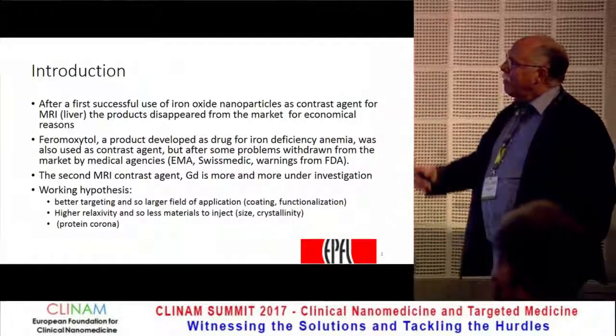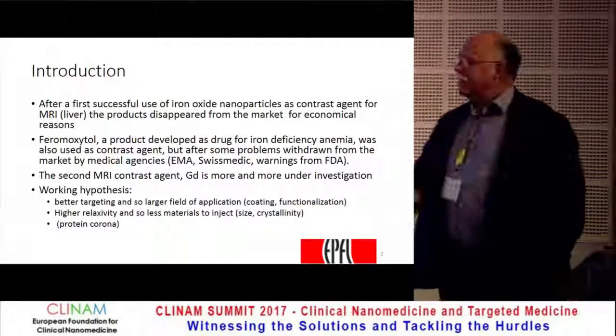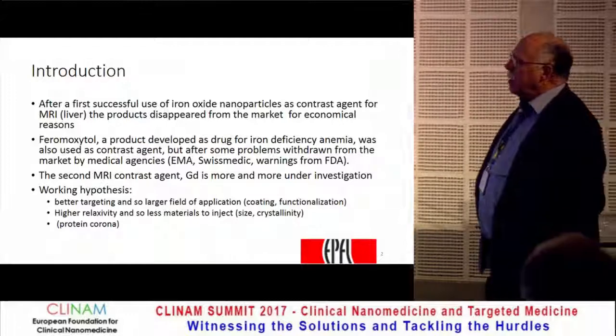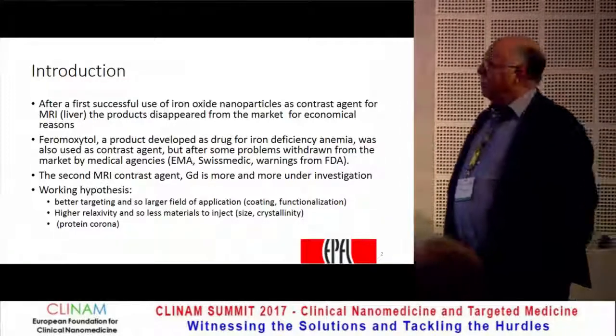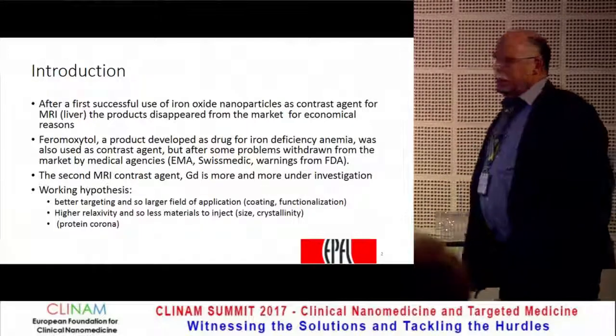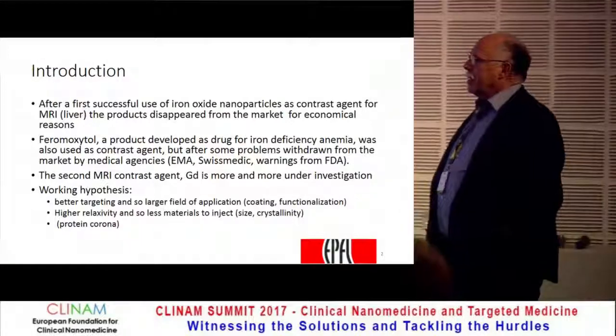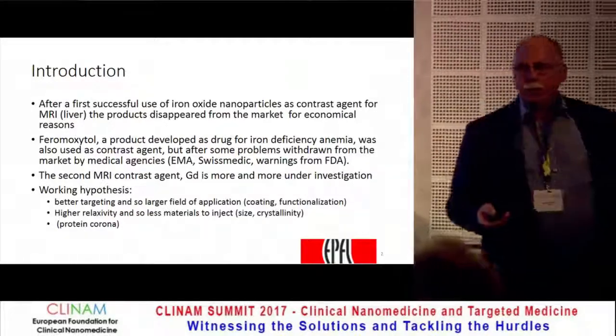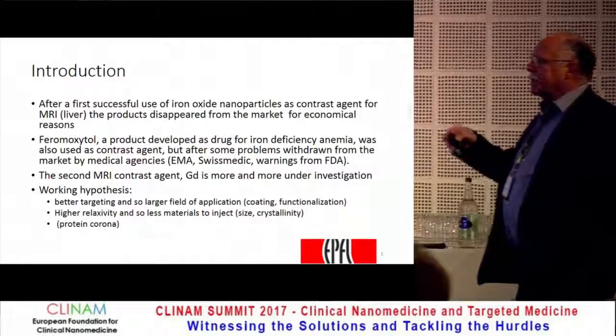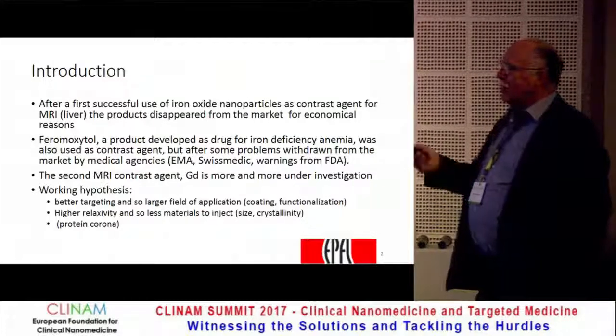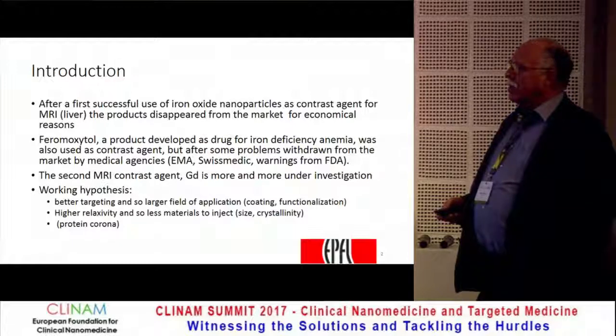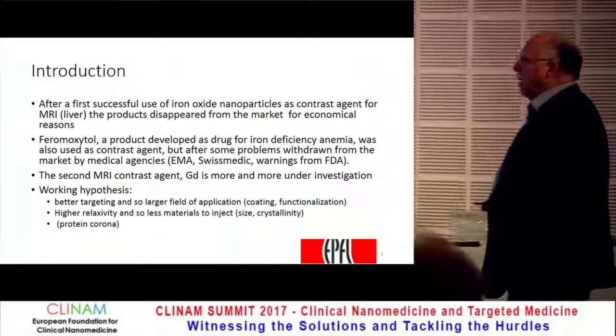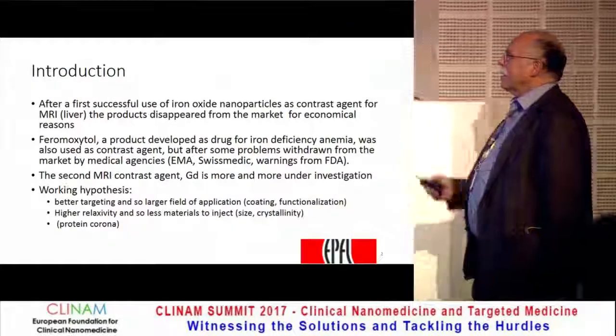Gadolinium is now also increasingly under investigation because gadolinium is found in the brain as a contrast agent. So we have a real problem with inorganic contrast agents. Our working hypothesis was: if you have a problem on the market side, then we have to go for better targeting, open the field for other applications, better targeting or retention, specific retention in some organs. We need coating and functionalization to optimize this, and we need higher relaxivity so that with less material we have better contrast. And then we have the problem of the protein corona — a synonym for the interaction of the particle in a biological environment — which we also looked at to understand what happens.